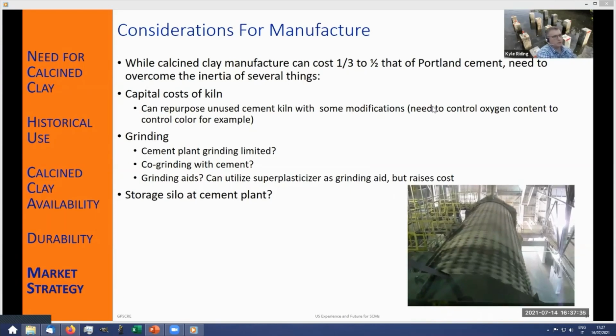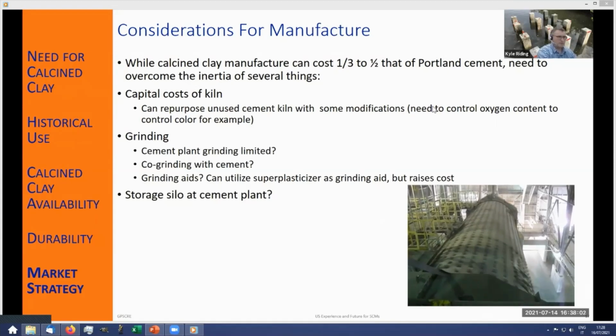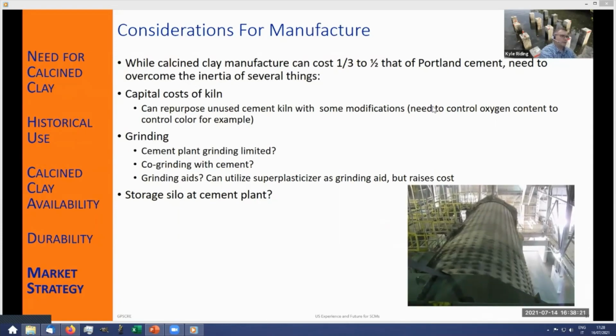There's also grinding. So if you're going to make a cement with calcined clay and limestone, you have to look at your grinding capacity. Are you grinding limited? Are you going to co-grind it with the cement or grind it separately? These grinding mills and ball mills can be very expensive to incorporate. Also, calcined clay, the highly reactive stuff, when you grind it fine, can reduce your workability, and that has a side effect of needing a superplasticizer to get the workability that you need. So yes, we can make the material at one third to half the cost of Portland cement, but you have to now use a superplasticizer, and that raises the cost and offsets some of the benefits of the reduction in material cost of calcined clay compared to Portland cement.